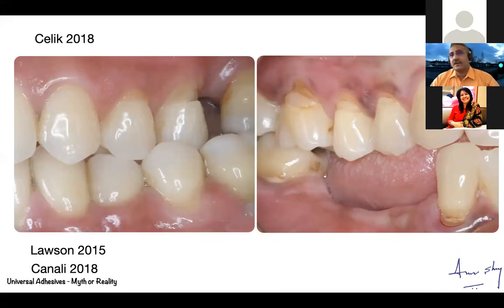So based on most available literature, few things I can tell you. There's not much of a difference between, say, a two-step self-etch and an etch and rinse. So two-step self-etches work wonderfully well here, except maybe over a period of time, the marginal discoloration is a little more. There's a study, I think, by Peumans. There's a 13-year follow-up where they have found that it works very well, self-etch. The other thing is, when you compare etch and rinse with self-etch, both are kind of similar. The viscous glass ionomers tend to have a little inferior performance compared to composites. So if you're using glass ionomers, the failure rate again may be slightly higher.